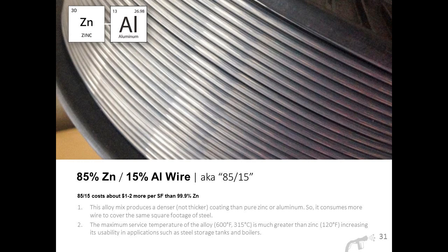Its maximum service temperature, as we talked about before, is 600 degrees Fahrenheit or 315 degrees Celsius. It's obviously much higher than zinc, but in terms of the bridge industry, that doesn't really mean a whole lot. 8515 can be used as a substitute for pure zinc because it's somewhat more chloride resistant while retaining good adhesion. And this is really the other distinguishing factor of aluminum versus zinc. If you take a look at the adhesion test results, you'll find that the adhesion for aluminum is a little bit higher than it is for zinc. But zinc certainly meets all the requirements that are necessary. So it's really just a question of what do you need, and do you feel like you need to go above and beyond what zinc can provide.